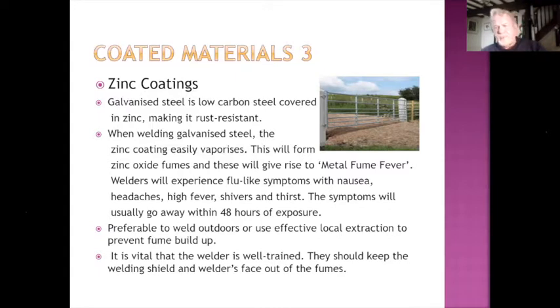If you want to do some repair on that, I advocate the use of a brass or a bronze material, because it will alloy with the zinc. You won't need to take off the zinc coating. Brass is a copper-zinc alloy, and you will find that it gives you flexibility and strength, especially in things like gates, where there is a potential for fatigue. It's preferable to weld outdoors, again using local extraction to prevent fume buildup.